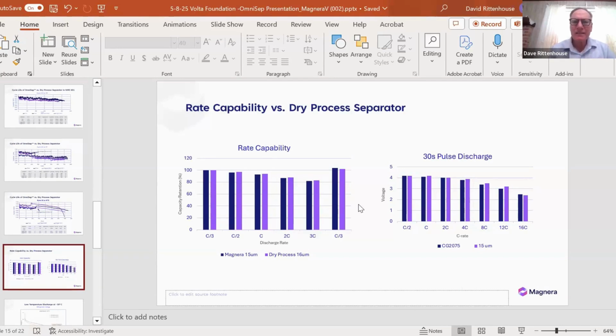Trying to tease apart rate capability, we used first a C/3, C/2, C, 2C, 3C, going back to C/3, comparing the two, the OmniSep with the Celgard, they're virtually identical. Another test was the 30-second pulse discharge, going from C/2, C, 2C, 4C, 8, 12, and 16. And there was a decline, but they were virtually the same.